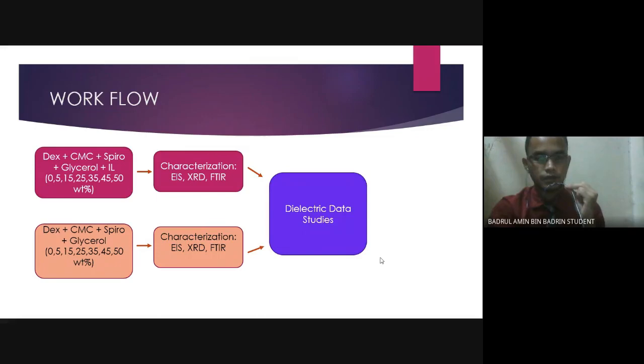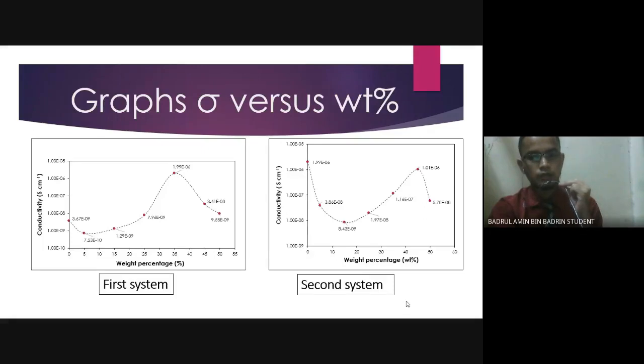So this is the first graph obtained from the first characterization. In this graph, the characterization of EIS focus between conductivity and weight percentage. As you can see on the left, the highest conductivity obtained is when the sample with the weight percent with the ratio of 35%, while the second system, the 35% ratio sample is being used in the second system, and it is successfully enhanced to 1.01 to the power of negative 6 Siemens per cm.